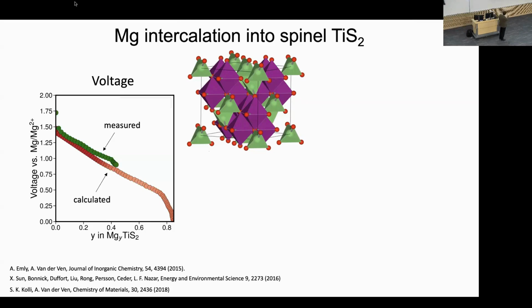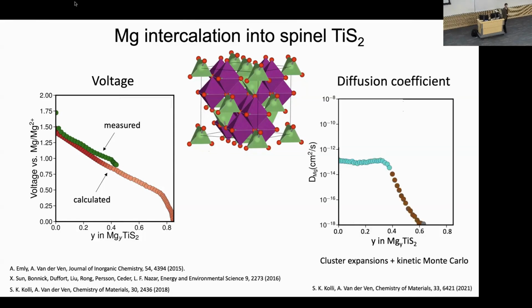Now, what you can see is that experimentally, we're only getting up to about 0.4, 0.5 magnesium into this compound. But our calculations indicate you should be able to get much more magnesium into this compound than 0.4. So that made us curious. And a few years later, we went ahead and calculated the magnesium diffusion coefficient. And this is what we predicted. We get a roughly constant diffusion coefficient up to about 0.4. And then once we hit this composition, you can see the diffusion coefficient suddenly crashes out, by almost 4 orders of magnitude.